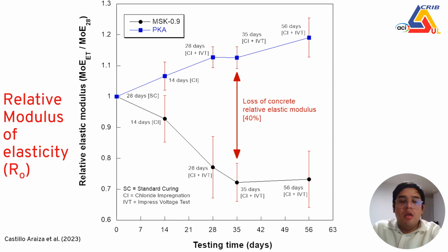To be able to compare two different sources of aggregate, or another source of aggregate, we are proposing a new measurement that we call relative modulus of elasticity. It is based on the modulus of elasticity obtained at 28 days of curing compared with the results that we obtain after some electrochemical treatment, 14 days, 28 days, 35 days, or 56 days. I am presenting here how the concrete performs after this treatment, and you can see how the reactive aggregate is losing on this property, while in the non-reactive aggregate it is gaining some on this property due to the hydration of the cement paste.